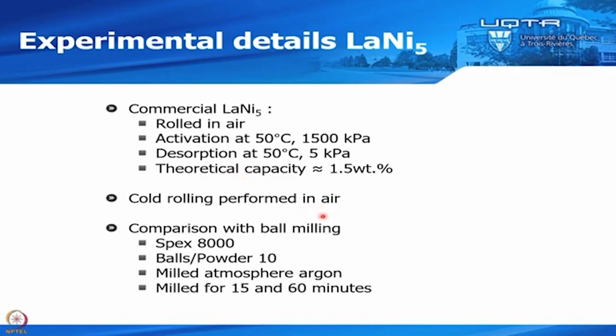And we compare that with ball milling because ball milling is used by everybody, and everybody knows what this ball milling is doing to metal hydride. So we use a high energy mill, and the milling was done in argon, contrary to here that was done in air, and we mill for 15 and 60 minutes.